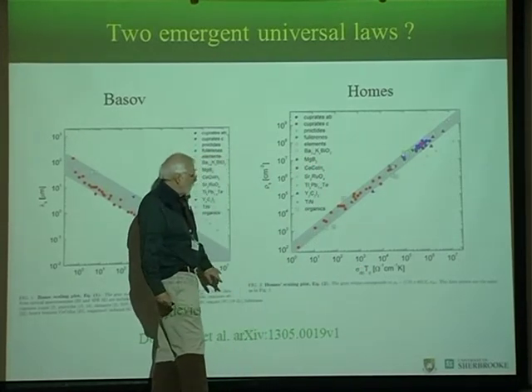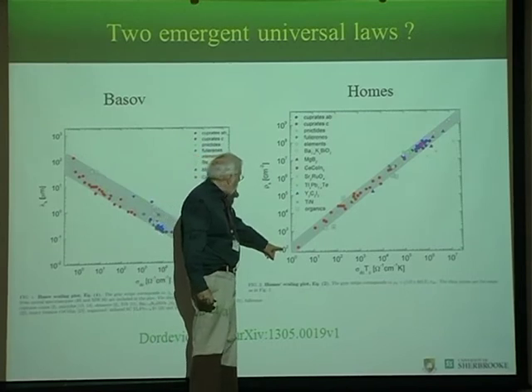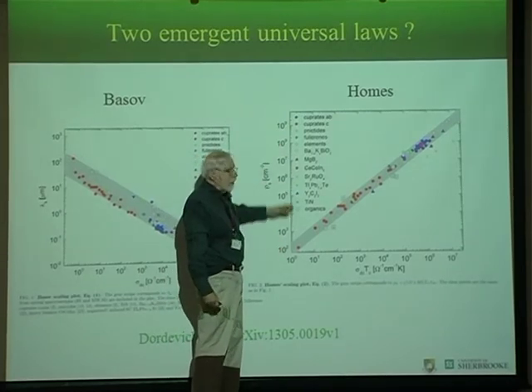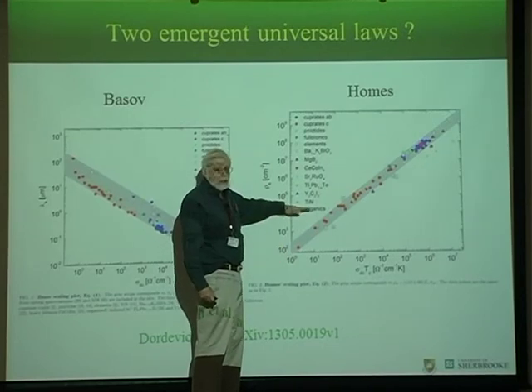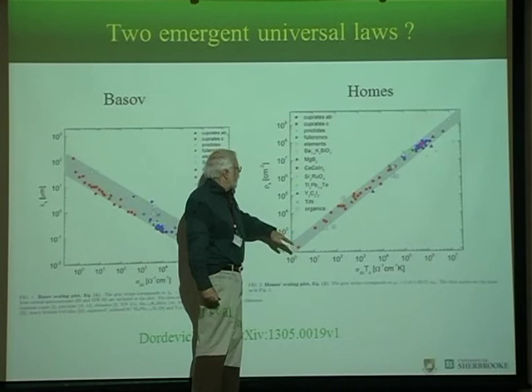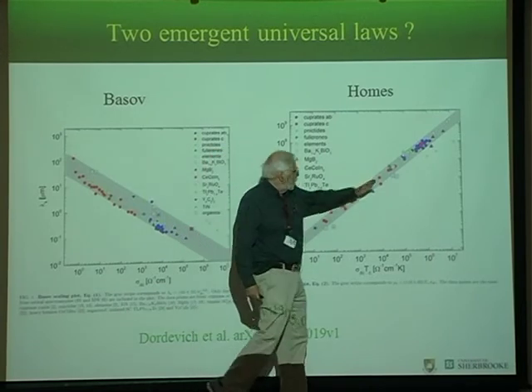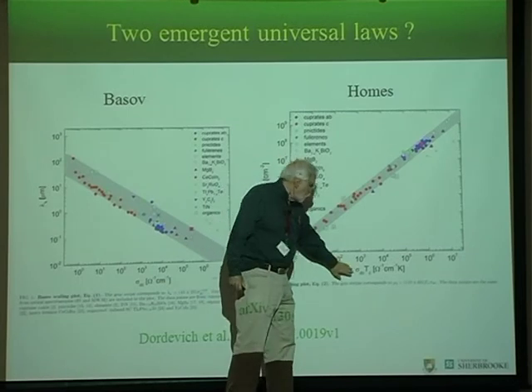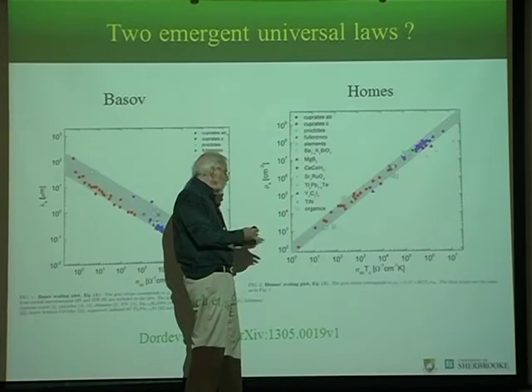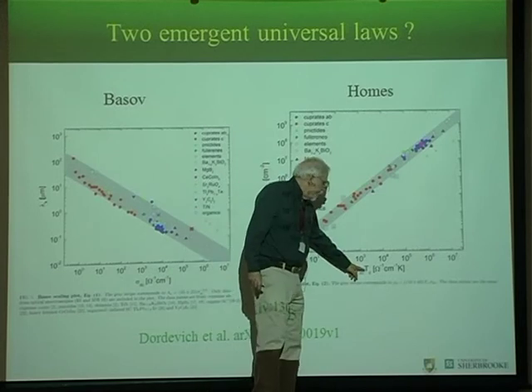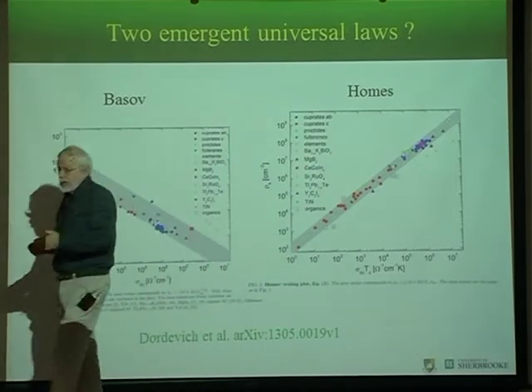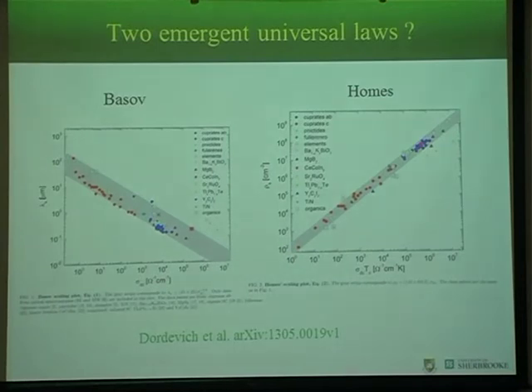Then you see that this is quite impressive. You have 10 to the 2 here and 10 to the 9 here. So you have 7 orders of magnitude. And these are all layered superconductors, and they all fall on this law. So this is proportional to this with the power law 1. If you just look at the dimensional analysis, you realize that it corresponds to assuming that at Tc, the scattering time is h bar over kBT. Sometimes people call that Planckian dissipation.